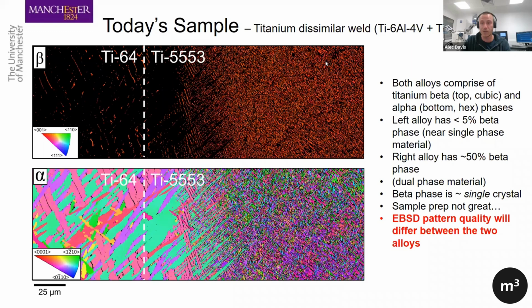We should also tell you what sample we're using. So we'll be using a titanium dissimilar weld sample. Now this is effectively 2 different alloys welded together. On one side we have Ti64, and on the other side we have this Ti5553. Now for those of you who aren't familiar with titanium, in these types of alloys, which are the most commonly used alloys, you'll find 2 phases present. You'll have the cubic beta phase, which is shown in this orientation map at the top. And then you have the hexagonal alpha phase in between, which is shown in this bottom orientation map. Now, the thing to notice is that the beta phase is all one single orientation.